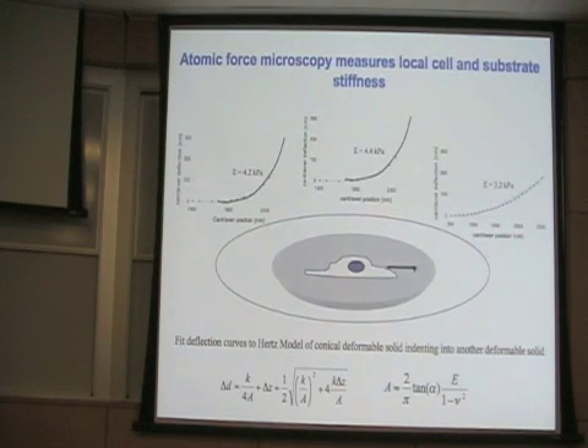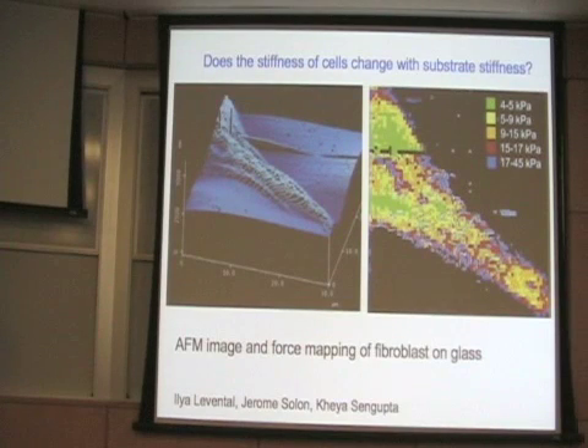Okay, so that's that. And the result is this, that here's something that people have seen since they first started to do atomic force microscope measurements of cell stiffnesses. If you take a very rigid material, two things are pretty evident from, in this case, this is a fibroblast protruding on a plastic surface. One is that on this kind of pixelated stiffness map, where each pixel is about 50 by 50 nanometers, there's a fairly large heterogeneity of stiffnesses.